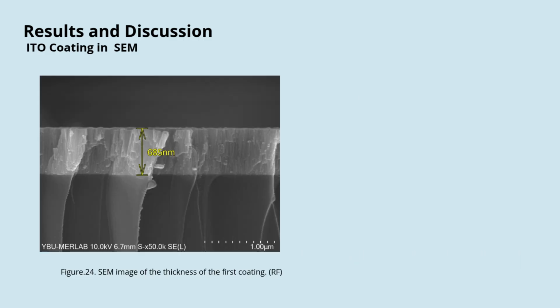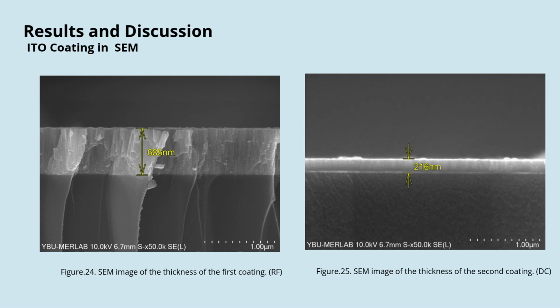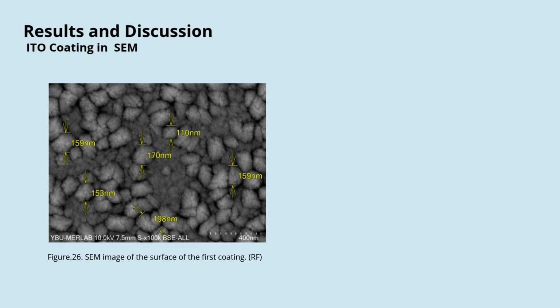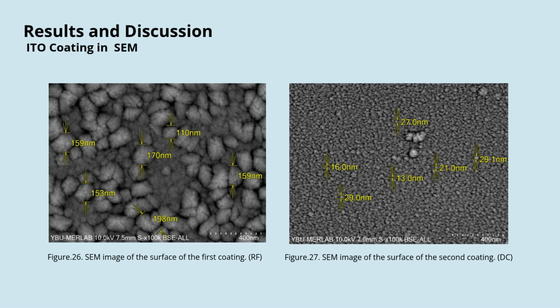When the coating thickness was measured in SEM, it is seen that the first coating is 3 times thicker than the second coating, which was expected as it was coated 3 times longer. The non-conductive nature of the second coating can be attributed to its thin layer. In the surface SEM image, we can see that the RF coating has bigger grain sizes than the DC coating, which shows that the coatings had different structures depending on the sputtering conditions.